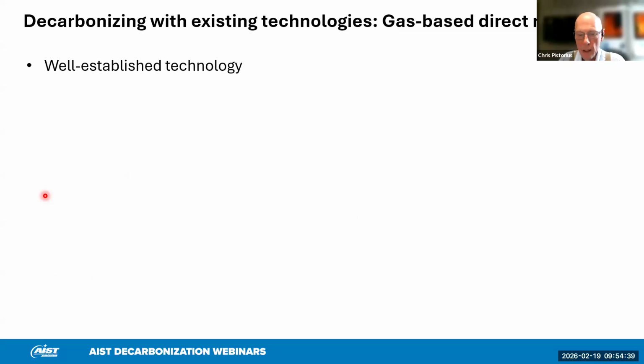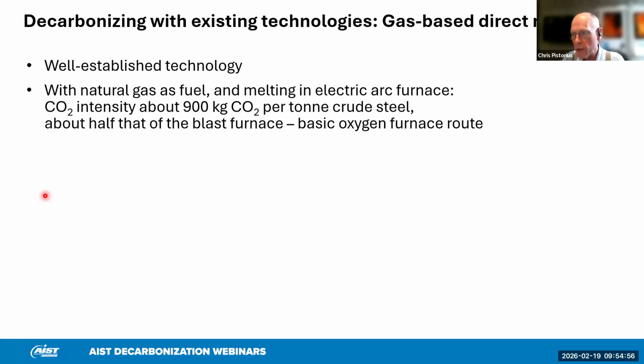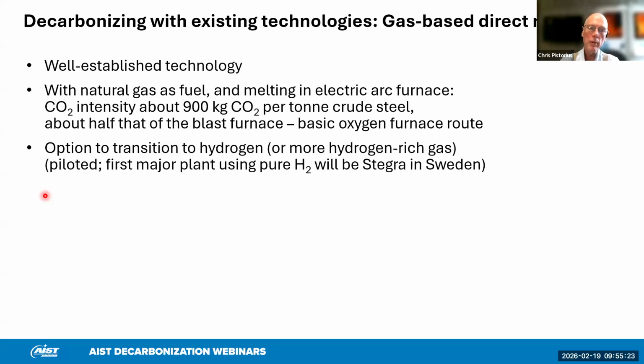The other existing technology that already reduces the carbon footprint of iron making by about half compared with blast furnace BOF operations is gas-based direct reduction. That is well established. We saw the production numbers earlier. And if you add in the consumption at the electric arc furnace, the total intensity per ton of crude steel is about half that of the blast furnace. This excludes some of the Scope 3 emissions from pelletizing. And there is the option to transition from natural gas to hydrogen.